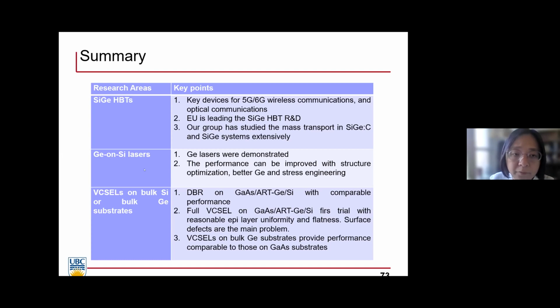Germanium on silicon lasers are relatively new in research, and they can be improved and optimized through better germanium quality and stress engineering. For VCSELs on bulk silicon or on bulk germanium substrates, we have demonstrated on par performance DBRs on this ART, aspect ratio trapping germanium on silicon. And the first full VCSELs have okay uniformity only locally, but there are some surface problems. And on the bulk germanium substrate, VCSELs are successfully demonstrated by IQE. So with this, that's the last slide, and thank you so much.